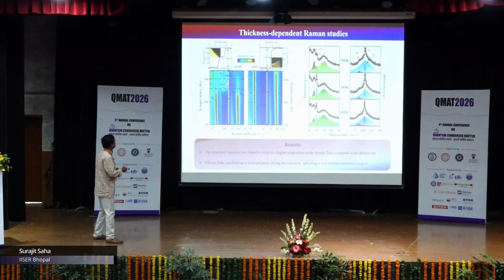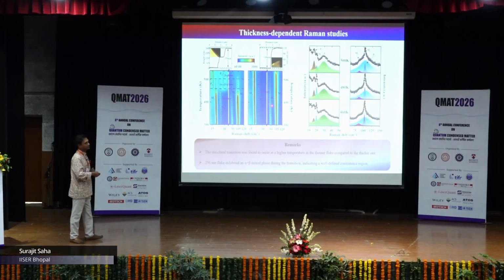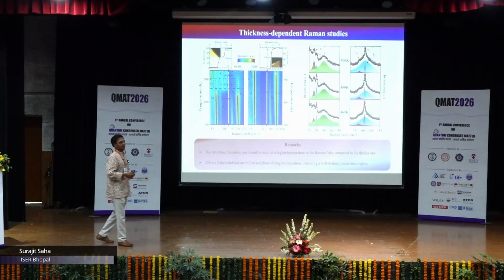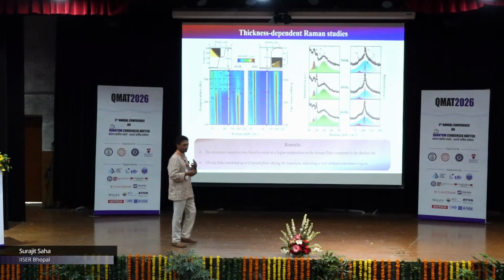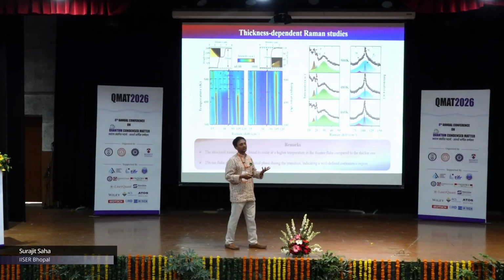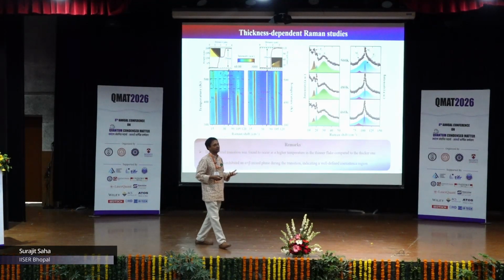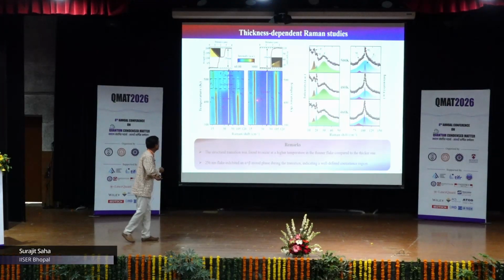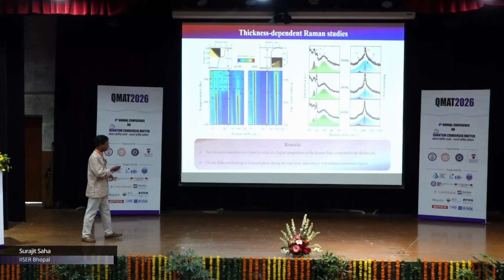and then it goes to the complete beta phase transition. On the contrary, if you take about a 100 nanometer thin film, there is no phase transition happening up to a temperature of about 550 Kelvin. We tried to go beyond that temperature, but then the sample gets degraded. So we couldn't establish the phase transition for the thinner flakes.